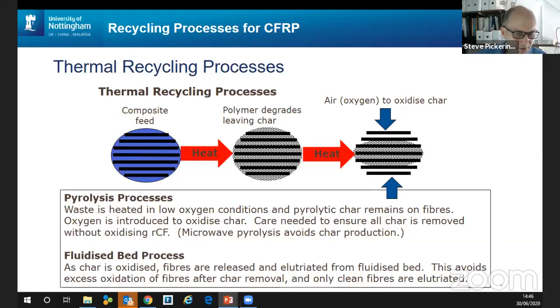But this is where the fluidized bed process has an advantage, because once the fibers have been released on the outside here, they're removed within the fluidized bed and elutriated, as we say. So effectively the fibers get removed from the process as soon as the char has been reduced, and so you don't overcook the fibers, and you don't need to worry about thick sections of material.